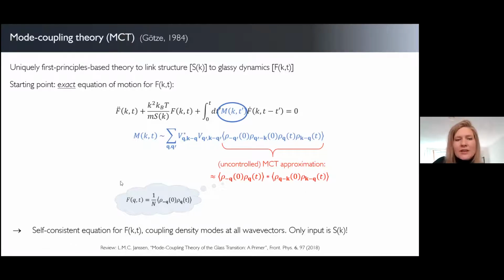And so what we end up with is actually a self-consistent equation for F(k,t). We write down this equation for F(k,t), and then via the memory function, we find that there are an F(q,t) and an F(k-q,t) here in the memory function. And in fact, we also integrate over all possible wave vectors q here in the memory. And so that's actually how you couple all the density modes for all possible wave vectors in the system through this memory function. And that's also where the name mode coupling comes from. So I hope that is clear, at least.